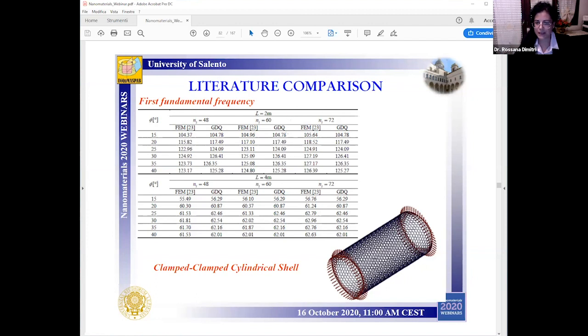And you can see here the results for two different lengths where we vary the helical angle phi from 15 degrees to 40 degrees by steps of 5 degrees, and by assuming also different numbers of helical ribs. So for a fixed length and helical angle phi, you can see that the increased number of helical ribs doesn't lead to a significant variation in frequency. But an increased length of the cylinder from 2 meters up to 4 meters consistently reduces the vibration frequency for the same values of phi and ns, I mean the number of helical ribs.